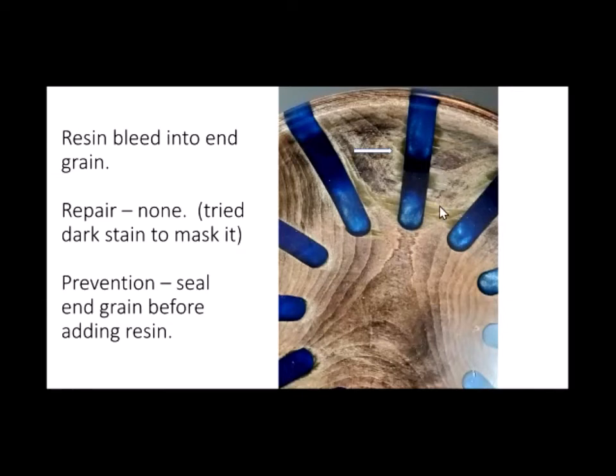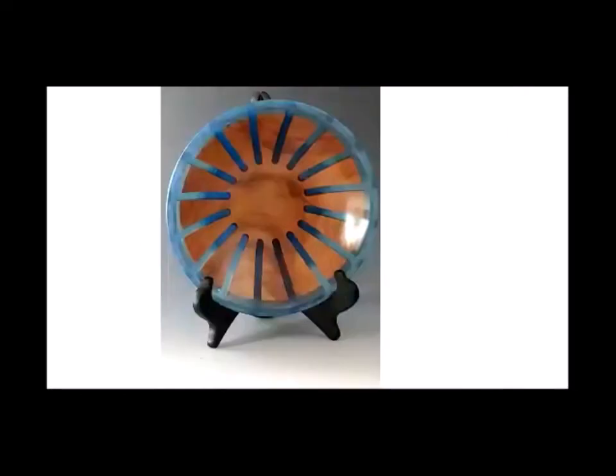So the remedy for that is this, a different cherry bowl, but you know, the same ribbing effect in it. On this one, I used 2 coats of sanding sealer on the inside edges of all those grooves before I cast the resin in it, and didn't end up with any bleed into that at all. So, lesson learned there.